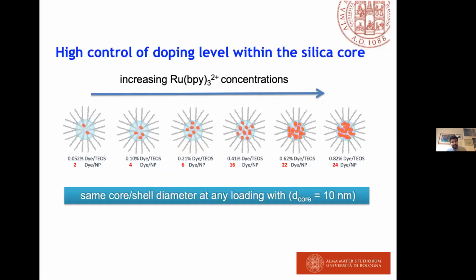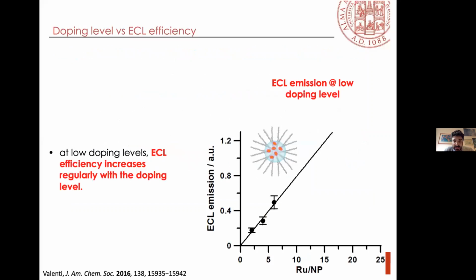But more interesting, I think, is we can use this synthetic approach to add in the nanoparticle different amounts of ruthenium. So we can exactly prepare nanoparticles with the same shape, with 2, 4, 6, and increasing the ruthenium concentration. And this is amazing because we can use the same molecule, the same nanomaterial, and see how it changes the emission from 2 dyes to 24 dyes. And this is what we did.